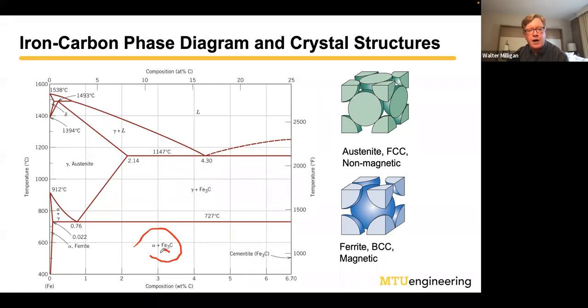It also has a carbide in there. That's the iron carbide, and that carbide is this line over here. If you look up here on the atomic percent scale, that's 25% carbon, so it's three irons and one carbon, Fe3C. This gives us two phases, and that iron carbide phase is going to be able to strengthen the material.